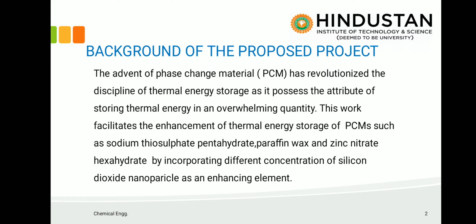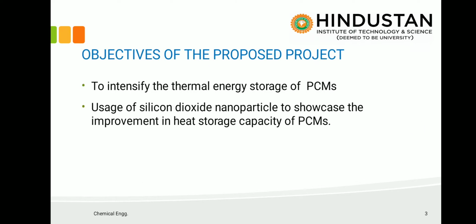So I have used three nano-PCMs such as sodium thiosulfate pentahydrate, paraffin wax, zinc nitrate hexahydrate by incorporating different concentrations of silicon dioxide nanoparticle. Here I have used silicon dioxide nanoparticle as an enhancing element. Objectives: to intensify the thermal energy storage of PCM, and usage of silicon dioxide nanoparticle to showcase the improvement in heat storage capacity of PCMs.